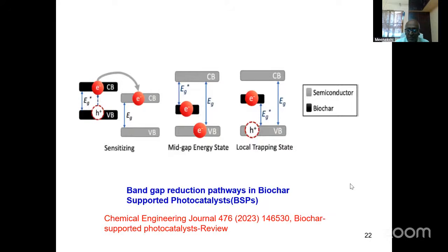And when you support this biochar with a photocatalyst, the band gap varies. Biochar is not a strong photocatalyst, but it has a very low energy gap. So the electron can go to the conduction band of the semiconductor oxide, or, just like metals, it can form intermediate levels, producing a local trapping state and also a mid-gap energy state. This review journal gives the detail about all these things.